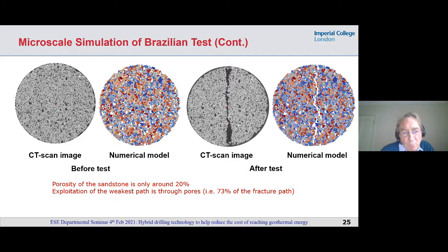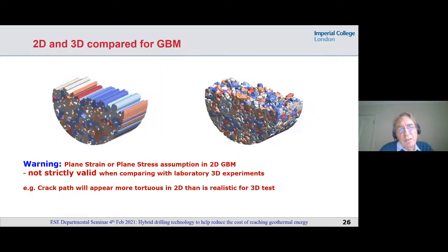Some highlights here. I've just said that with our 20% porosity sandstone, we find that we exploit a weak path where something like 73% of that path length is going through void space. Now, I'd just like to highlight, this is beautifully published in a paper by Bin Chen. And what I wanted to show you here is a warning that when we simulate in 2D, what we have is not really the real thing, because what we're effectively modeling in plane strain or plane stress is a kind of extruded situation rather than a fully 3D granular situation. So of course the path is going to be more tortuous than it would be if it were exploiting all the nearby grain boundary surfaces available in an actual 3D test.